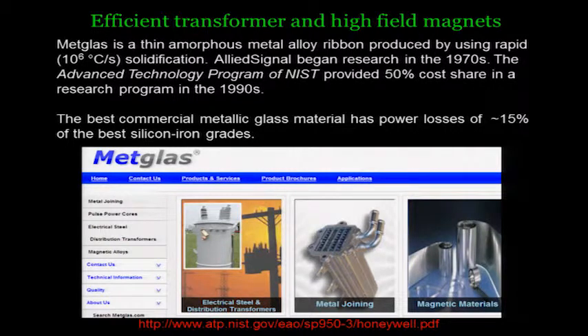In fact, the Department of Energy sponsored a research program in the 1990s that essentially did what's called splat cooling. You get a metallic material, you cool it very rapidly, it splats on a surface and conducts heat away, and you make a metal glass. This stuff is about 85% more efficient than your standard silicon iron magnet material. Now, the sad thing about this is AlliedSignal didn't have the staying power. They got it, and the company was bought out by a foreign company.